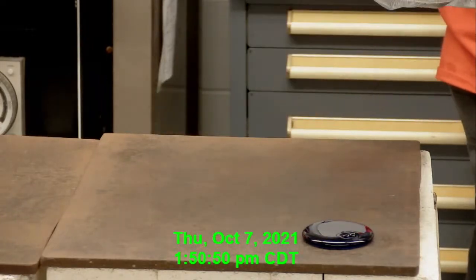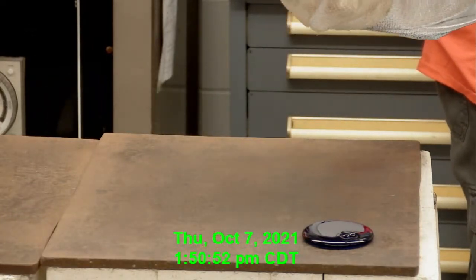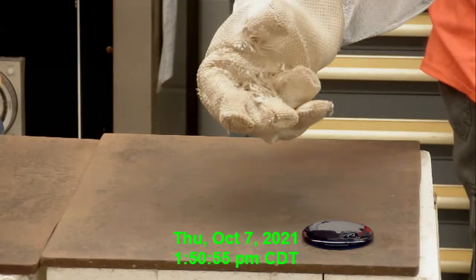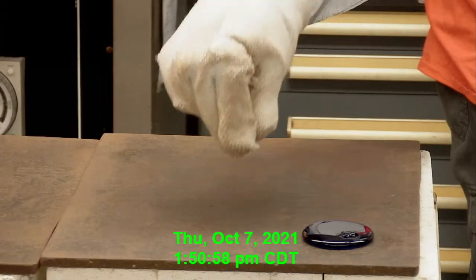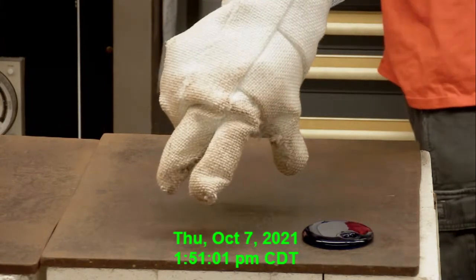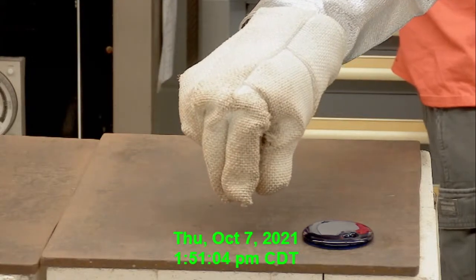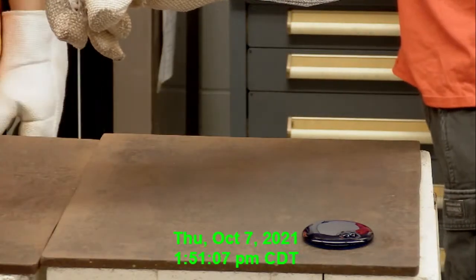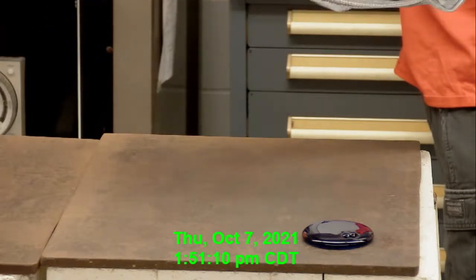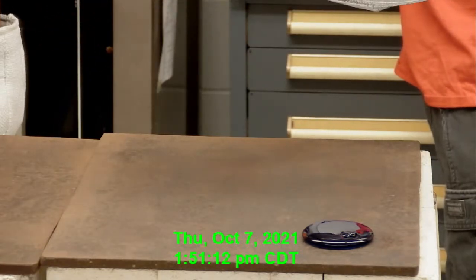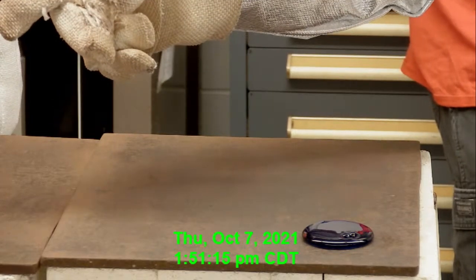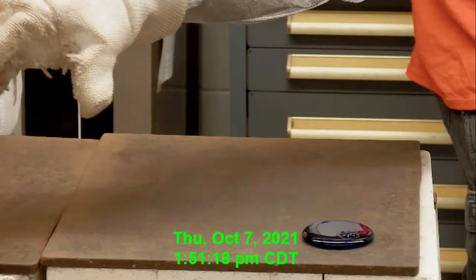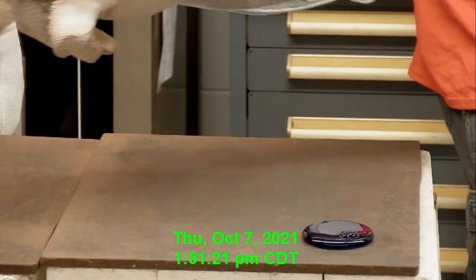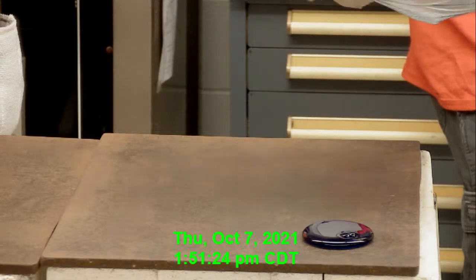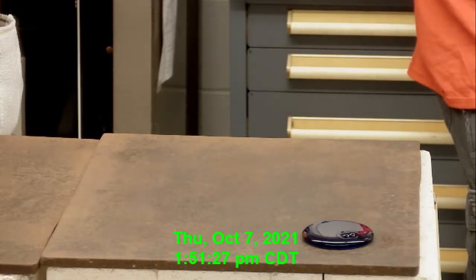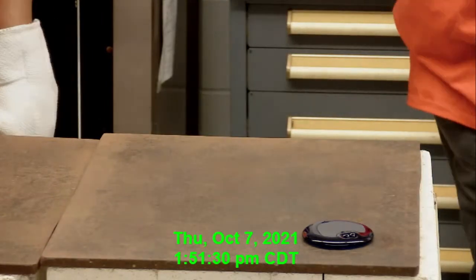Now as we're pouring, watch for subtle differences in viscosity. So how thick the liquid looks as it's being poured. A low viscosity spreads out a lot, a high viscosity spreads out not as much. You'll also hear what's called crazing. What you're hearing is little cracks forming in the glass because it shrinks at a different rate than the ceramic. So shortly you'll hear lots of that going on as we get more and more crucibles. But that little sound, every time you hear that, there's a new crack that's forming in the interior glass. So anyway, so we'll pour the next one right there. So N1, yes.